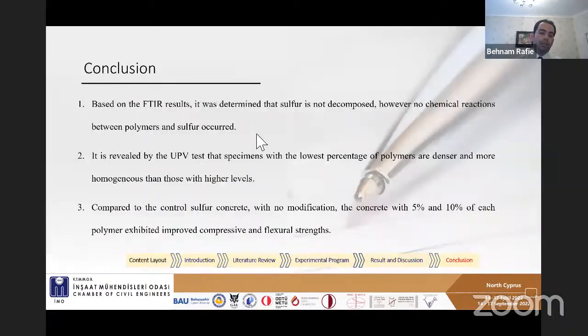As a conclusion, based on FTIR test results, it was determined that the sulfur is not decomposed. However, there is no chemical reaction between polymers and sulfur. It's revealed by the UPV test that specimens with the lowest percentage of polymers are denser and more homogeneous than those with higher levels. And compared to the control sulfur concrete with no modification, the concrete with 5 and 10% of each polymer exhibited improved compressive and flexural strengths. And these are my references in literature review.